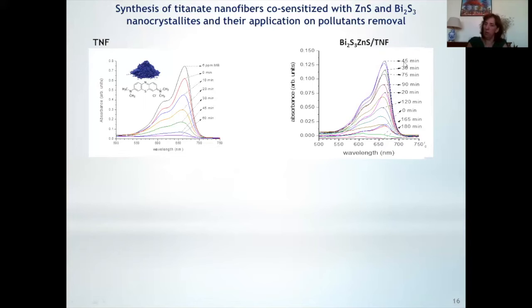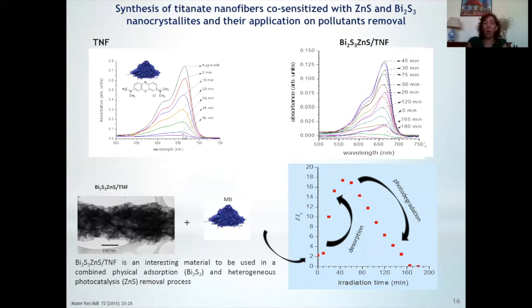And only after 45 minutes, I start to see the decrease of this absorption. Why? Well, first, we have the bismuth sulfide that is an excellent adsorbent. So it's adsorbing the dye. And after, at time zero, we start the irradiation.